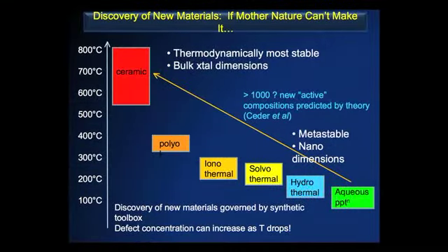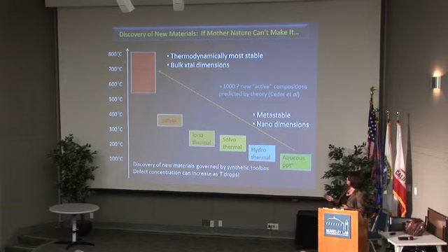So we have to rely on techniques that are not perhaps common to the solid-state chemist, ones in which we deviate from these classic ceramic methods and move down the scheme, although the arrow shows going up, into these other sorts of processes where we carefully control the chemistry so that we can access metastable materials, ones that would literally decompose at the higher temperatures, and also possibly access nanodimension materials, because ultimately high temperatures lead to large aggregation and large crystallites. So the ones that we know, the ones that we're particularly familiar with, are always the ones that Mother Nature makes, thermodynamically stable ones of bulk dimensions. Now, Gerbrand Ceder has calculated well over 1,000 new materials, and so the hunt is on, and the question is how to actually get them.